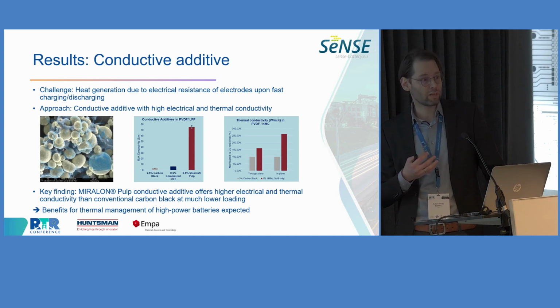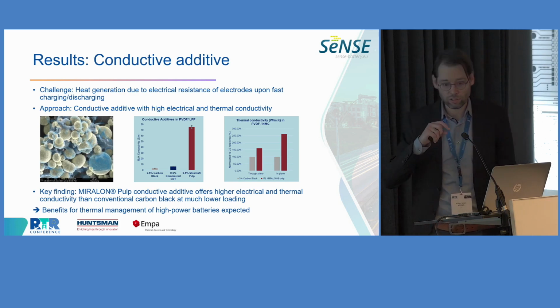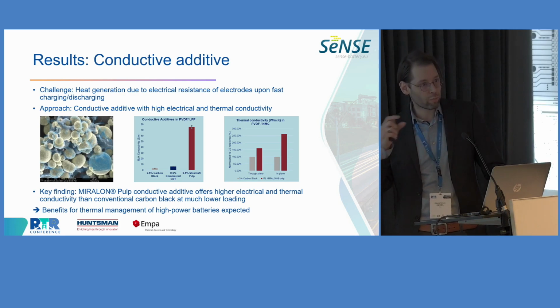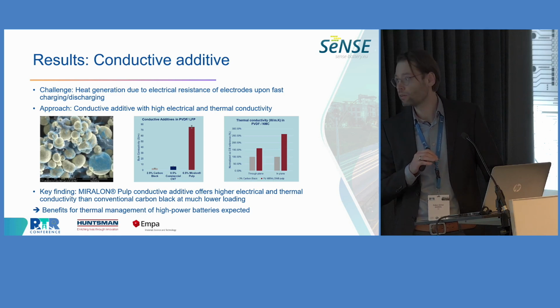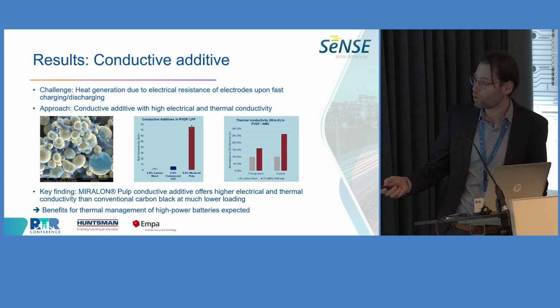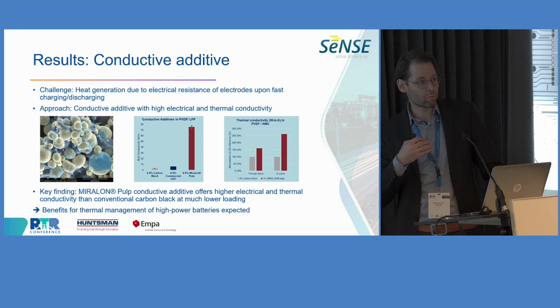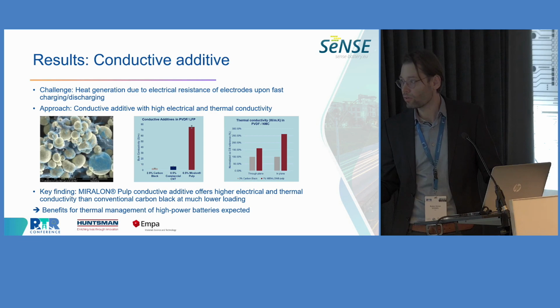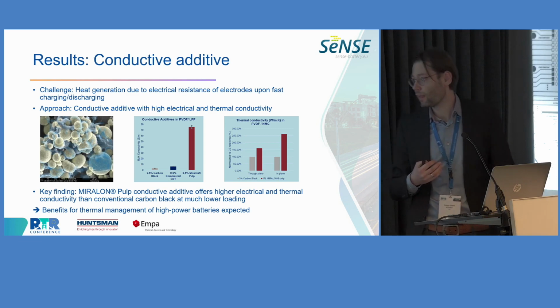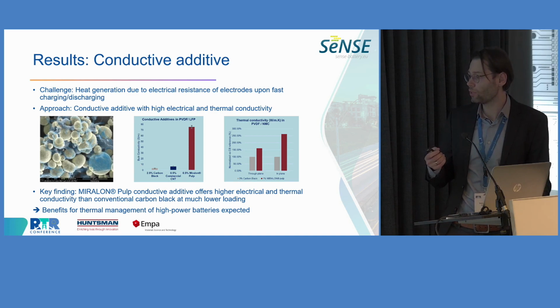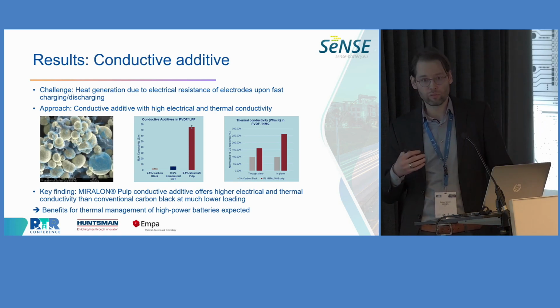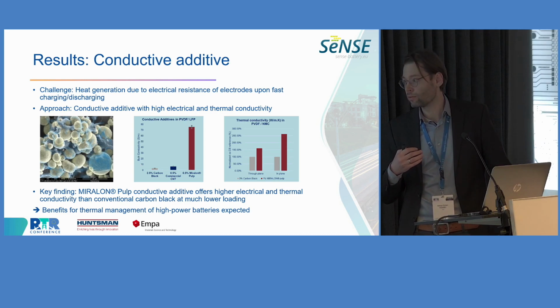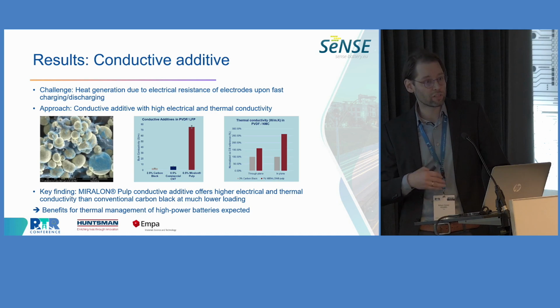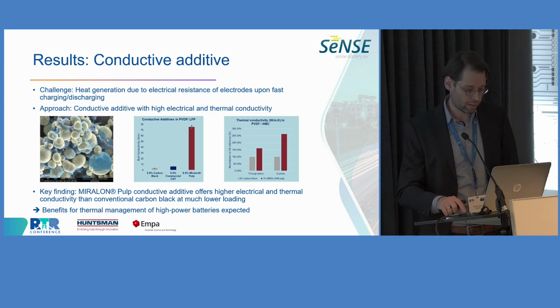And this has kind of a dual benefit, because we are on the one hand generating now less heat because the ohmic resistance of the electrode is lower. So if we fast charge or discharge the cell, we generate less heat. And at the same time, it becomes easier to dissipate the heat using this material. And it has a quite interesting morphology. So it's a CNT-like, so carbon nanotube-like material that wraps itself around the active material particles. And we are at the moment investigating really how the use of this conductive additive benefits the thermal properties on the cell and even pack level.